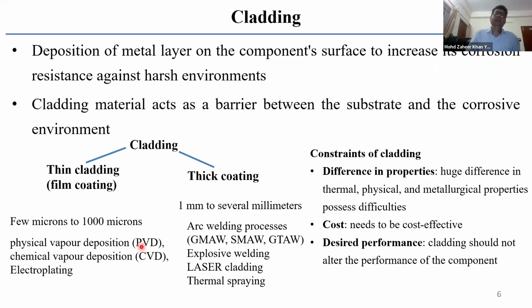Now let us talk about cladding. Cladding is, as I have defined, a deposition of a material layer on the component surface to increase its corrosion resistance against a hard environment. The cladding material actually acts as a barrier between the substrate and the corrosive environment. The cladding that we have deposited can be either a thin cladding or thick cladding. Thin cladding is also known as film cladding. These thin claddings are generally a few microns in dimension. Maximum it can be 1,000 microns, and they are generally carried out by processes like electroplating, physical vapor deposition, chemical vapor deposition,